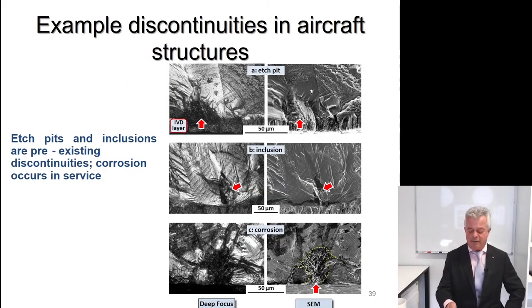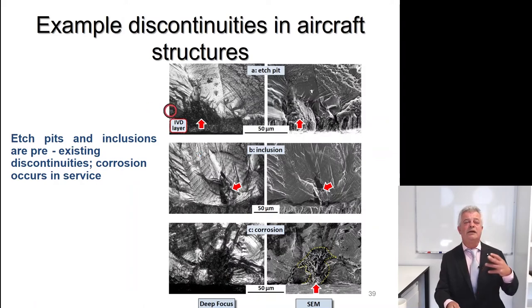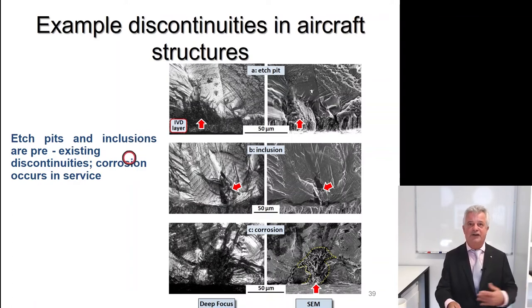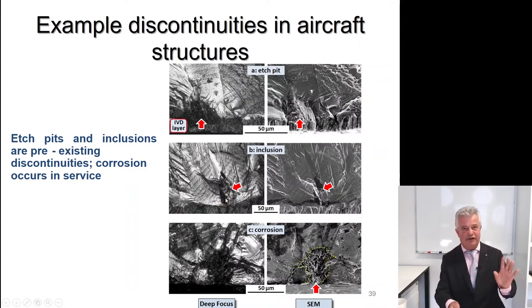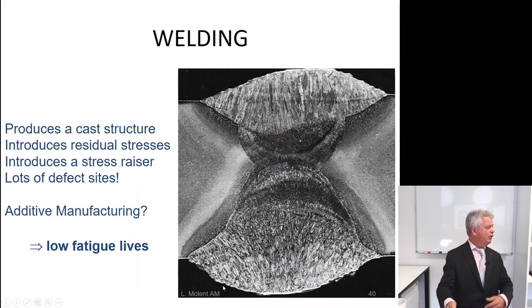Moving on, there are many, many discontinuities that can lead to fatigue. Some of them come out of the factory with the airplanes. These include surface finishes like chemical etching to clean the material. The material itself has hard particles that are close to the surface, and the machining, the grinding, will break them, and then they become very efficient crack starters. And I mentioned our good old friend corrosion that could nucleate things. I'm going to move along a little bit here.